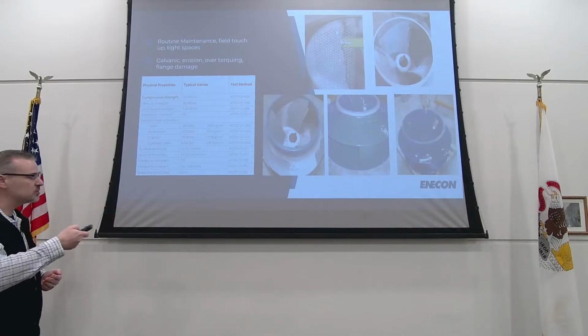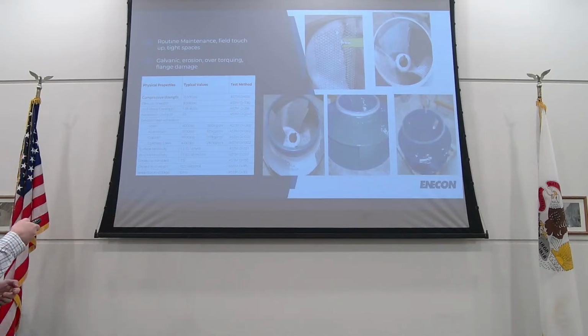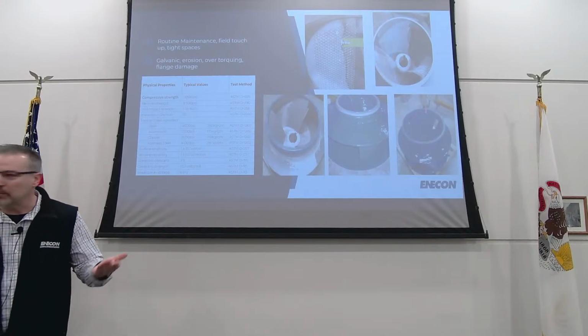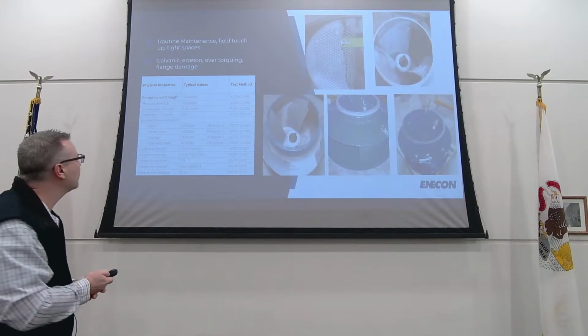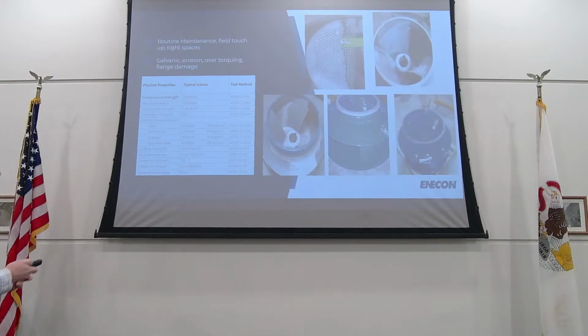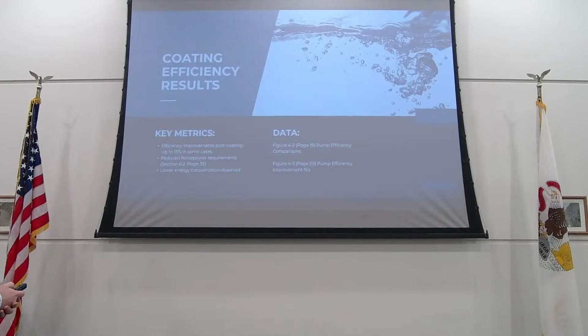When you have that great adhesion rate at 4000 PSI, if there was ever damage in that through erosion, through a heavy impact, rock, debris, it's not going to buckle and fail and just flake off all over the place. You might just have some localized repairs that one could do on a maintenance cycle. Maybe you do an annual inspection and get it back into service in a pretty fast fashion. So that was just what I need to see here.